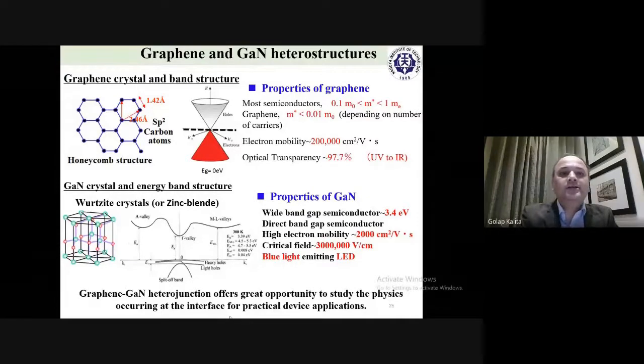I discussed graphene, so we know that it has very high electron mobility. And gallium nitride, as I said, is a wide band gap semiconductor of 3.4 electron volts. Carrier mobility is around 2000, a little bit higher than silicon, or almost similar to silicon maybe. Then the critical field, this is the important aspect. The critical field is very, very high.